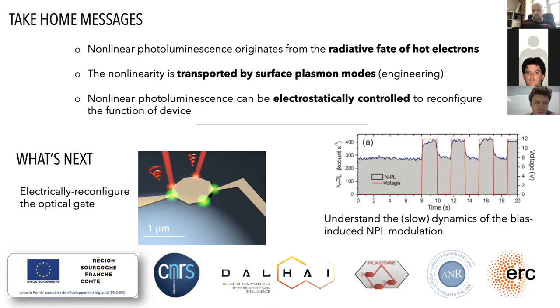So there are basically two things happening. I don't want to be too long on this because this is still under investigation, but there are defects that are created inside the gap in terms of oxygen vacancies. And the second type of defects that are created: you do electrochemistry by injecting gold atoms inside the gap that are forming clusters. And we don't know yet what is the precise role of these clusters in the dynamics of the NPL close to the electrode. We're still investigating this, but I would say for optical excitation, gaps are in the 30 nanometer range. For electrical excitation, we are in the tunneling regime.